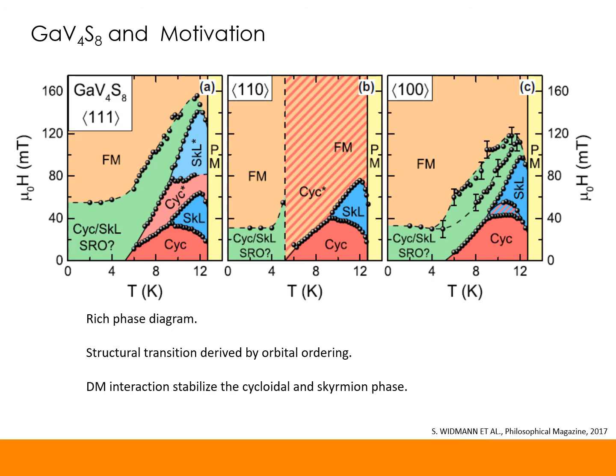GaV4S8 is attracting a lot of attention these days because of its rich phase diagram. Although the material has non-chiral polar crystals, it exhibits a skyrmion structure, which was theoretically predicted a long time ago, although it took some time to observe the skyrmion lattice experimentally in a non-chiral structure. You can see in the slide that this material hosts multiple magnetic ground states, including Néel-type skyrmion, cycloidal ground state, and conventional ferromagnetic ground state.